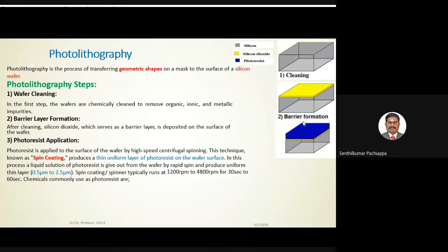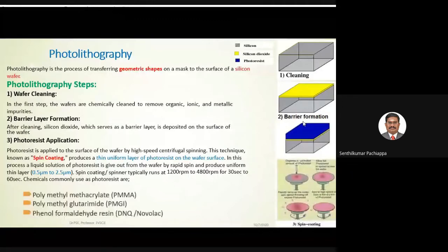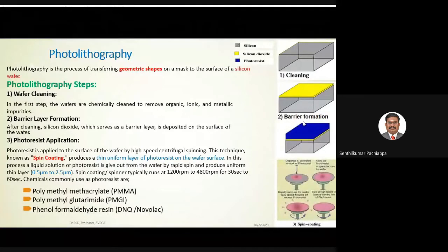Spin coating or the spinner typically runs at 1200 rpm to 4800 rpm for 30 seconds to 60 seconds. Chemicals commonly used in the photoresist are polymethyl methacrylate, polymethyl glutarimide, and phenol formaldehyde resin. These three chemicals are used for the photoresist.